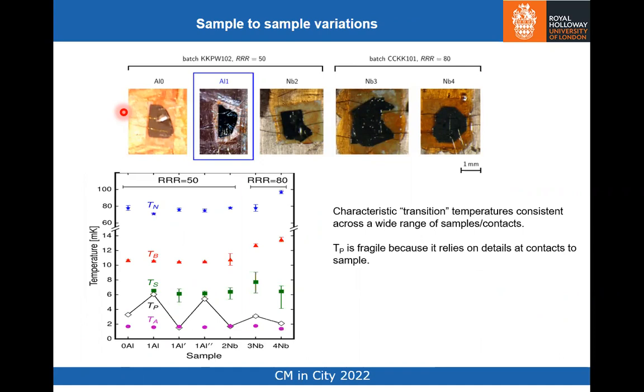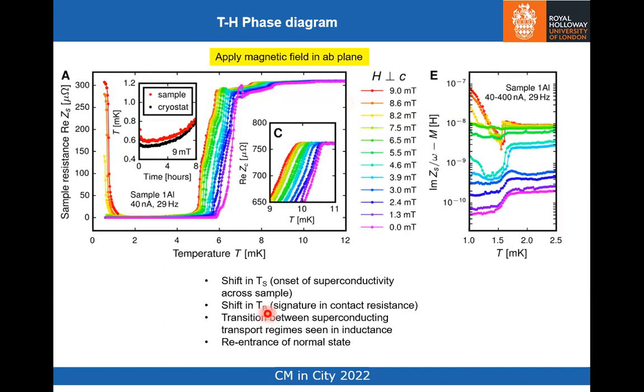So then you might ask the question, since this isn't helium-3, we have to worry about sample variations. So we study a whole bunch of samples, and all of these various transition temperatures that I've identified, the T_N temperature at 70 or so millikelvin, this TB feature in the contact resistance, the TS feature in the sample resistance, the TA feature in the sample inductance, are all robust across these samples. What is not robust is the ability to observe persistent currents, because that requires a continuous superconducting loop. So if something nasty happens in the contact region, one weak point can totally kill the ability to observe persistent currents.